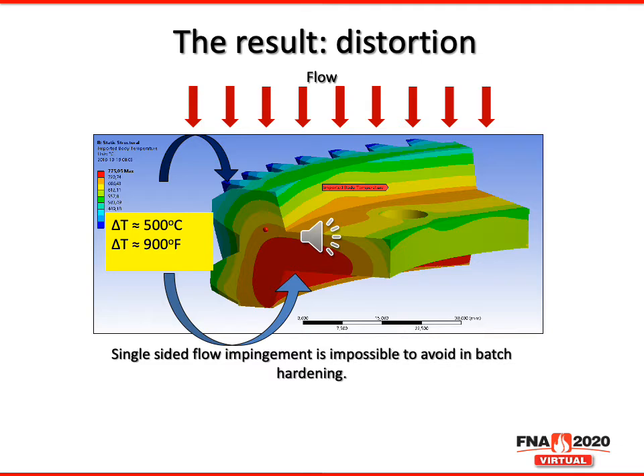Let's take this gear for instance. This flow variation has caused a 900 degree Fahrenheit temperature difference from one surface to another. Now, as you can imagine, the surface on the outside that is cooler is cooling and contracting much faster than that which is still warm. What does this do? It creates stress within the part, and that stress has to be released in some manner, and it's released as distortion.